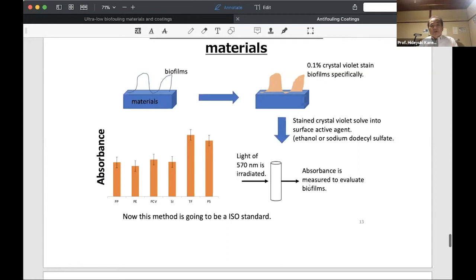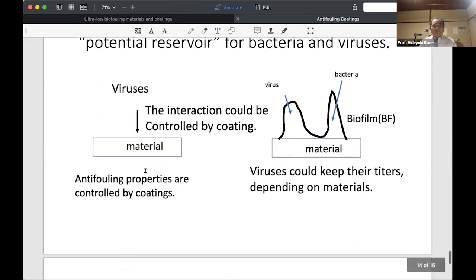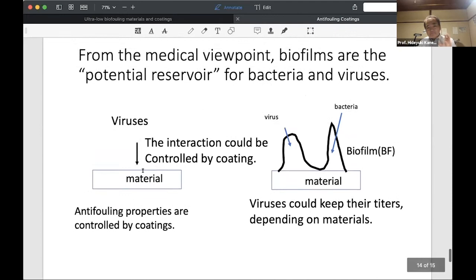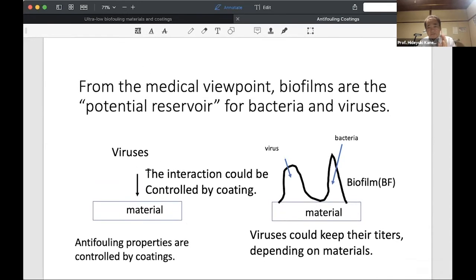Therefore, we can evaluate the biofilm quantitatively by measuring absorbance. And in such a way, we analyze the antibacterial, anti-fouling properties of materials. And at the same time, if we develop an anti-fouling coating, then we can evaluate the anti-fouling properties quantitatively and correctly by using this method.